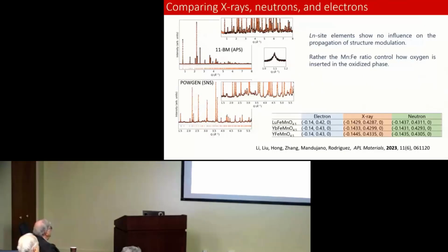And what those superlattice reflections are coming from has to do with a propagation vector that's a charge density wave from the oxygens as they insert into those layers. And it turns out that using the propagation vector that we were able to get from electrons, we were able to go back to the synchrotron source and fit all those satellite reflections, and also the POWGEN data fit those satellite reflections. So if we compare all three particles with each other, electron, X-ray, neutron, in the end, we're pretty sure we can come to the conclusion that you have sort of a 1/7, 3/7, 0 type of satellite that develops as you uptake oxygen into these materials.